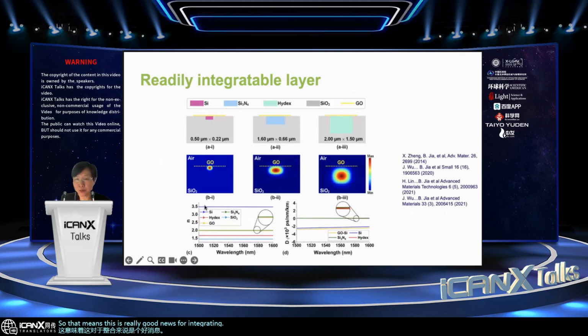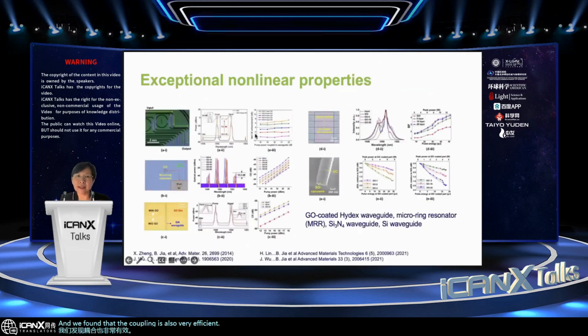So we integrate graphene oxide with different materials, including silicon, silicon nitride, Hydex, and silicon oxide. We found that the integration is really quite handy because of this self-assembly method. And we found that the coupling is also very efficient. And after the integration of this graphene oxide, the nonlinear property of these devices, all this integration have improved.